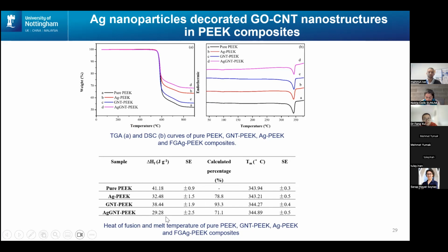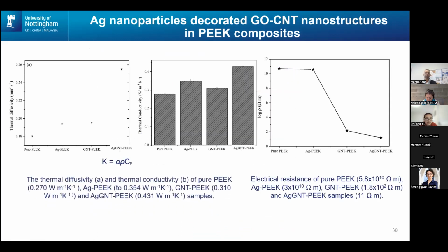But we will see how different they are in terms of properties. We measure the thermal diffusivity of those materials, and then we measure heat capacity. Using this equation, with the thermal diffusivity, heat capacity, and density, we can calculate the thermal conductivity. We can see thermal conductivity has improved comparing pure PEEK and silver-GNT reinforced PEEK — about 60% improvement, improved regardless of which composite it is.